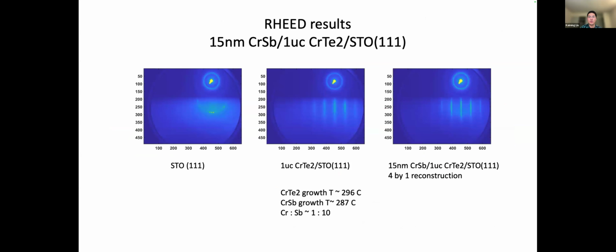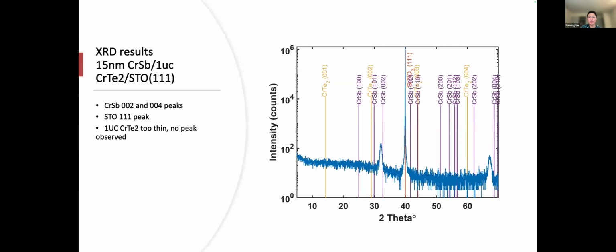And these are the RHEED results for the second recipe, 15 nanometer chromium antimony on 1 unit cell chromium ditelluride on STO(111). You can see sharp streaks and a clear 4x1 reconstruction after chromium antimony growth. And the growth temperature for chromium ditelluride was 296 and for chromium antimony 287, with a chromium to antimony ratio of about 1 to 10. And here are the XRD results for this sample. We clearly see chromium antimony 002 and 004 peaks, and the STO(111) substrate peak. The chromium ditelluride is only 1 unit cell, so it's still too thin to show up here.